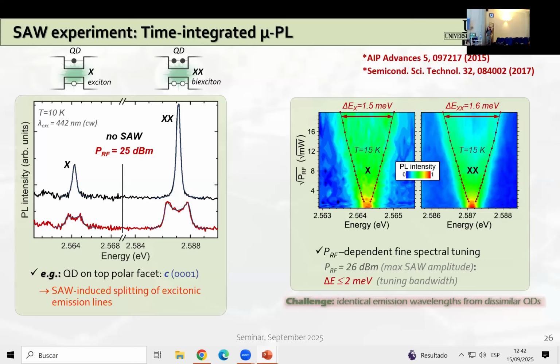So when we apply the acoustic wave now, what we observe is that these excitonic lines split, and we see that the magnitude of this splitting increases continuously as we increase the amplitude of the acoustic wave, meaning the RF power that we apply to the IDTs. The bandwidth of this splitting can reach some 2 millielectron volts for the highest possible acoustic amplitude. There's a limit actually of the RF power we can apply to IDTs so that we don't break them, which is around 26 dBm in our experiments.